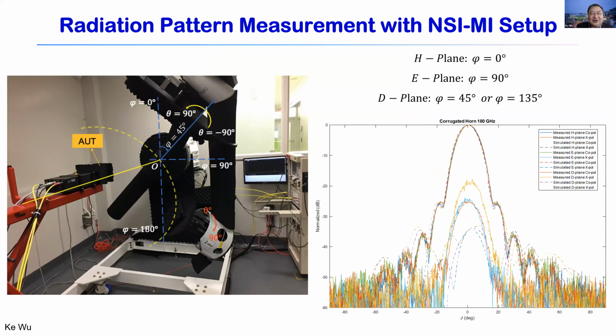So to measure the quality of the Gaussian beam, first of all, we use our NSI MI system, a robotized quasi-optical measurement system. We look at the corrugated horn launching the Gaussian beam to look at the beam quality at different angles. We use the 45 degree plane cut, 90 degree cut, 180 degree cut, different cuts to see how the beam looks.